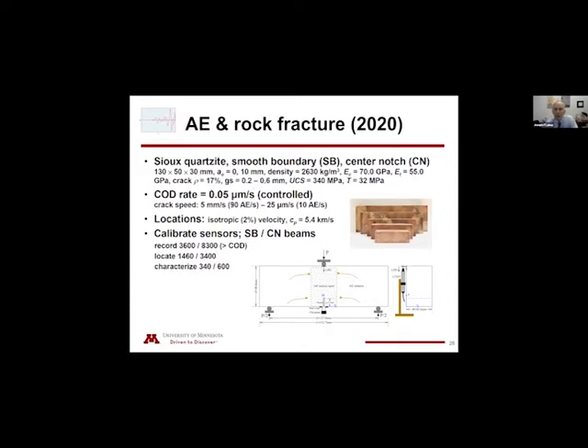The grain size is quite fine. Average size is around 0.3, 0.4 millimeters, and the strength is quite high. So this 340 MPa is on the order of 50,000 PSI. The tensile strength, measured in a beam test with no notch, is also high, 30 MPa, almost 5,000 PSI. We're using crack opening displacement as the control signal with the feedback signal within the closed loop system.